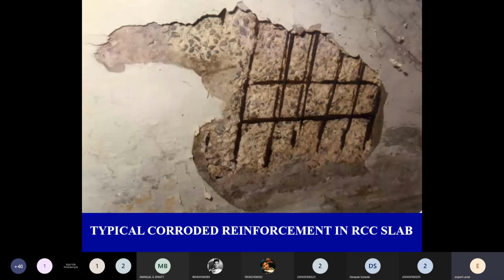So this was a typical situation where a person from a visual observation itself can say that this corrosion has happened due to seepage, because there was no other possibility which could exist in this case. Once we had done the chemical test and found that all the chemical ingredients are within the permissible limit, for these members, we designed ISMB 300 and placed them at a spacing of 1.5 meter center to center just to support this slab, because there we were not permitted to do any kind of damage or dismantling. So it was only to enhance the service life by some 15 years or 20 years.